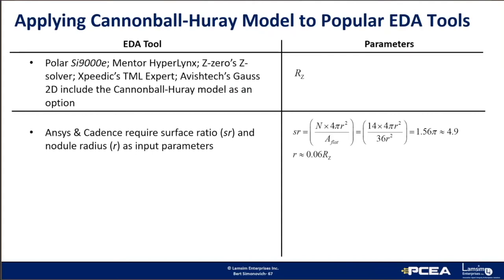ANSYS and Cadence require surface ratio and nodule radius for input parameters. Surface ratio is the part of the Hooray model. Because R squared cancels out, SR can be simplified to a constant 4.9, and nodule radius is calculated as 0.06 Rz. And that's all you need to do for these tools.